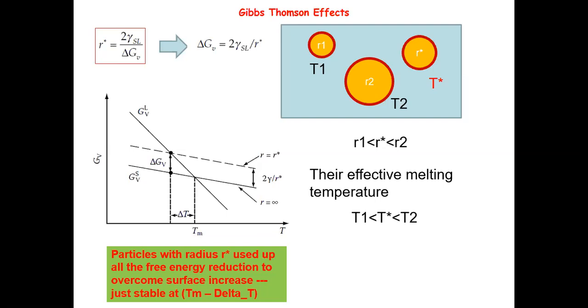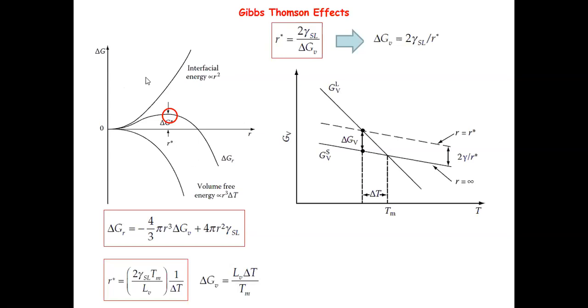Yeah, the question is that, from the Gibbs-Thomson, from our previous analysis, we know the radius is going to determine the fate of the particles, right? We know that for this supercooling delta T, we have the system at a temperature T star, and this supercooling is just enough to stabilize a radius of R star, right? So from the geometrical point of view, whenever the radius of the particle is greater than R star, it's going to grow. Any particle smaller than R star is going to shrink. This is what we did in the last lecture, right?